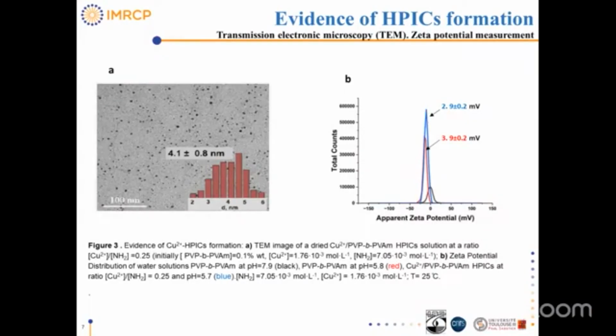Transmission electron microscopy shows small, high contrasted domains with an average diameter of about 4 nanometers, figure 3a. These domains presumably arise from the copper-rich complex core, and zeta potential, figure 3b, was measured at 2.9 millivolts for copper HPICs, whereas its value for a pure polymer solution is equal to 3.9 millivolts. It indicates a slightly positive surface charge.